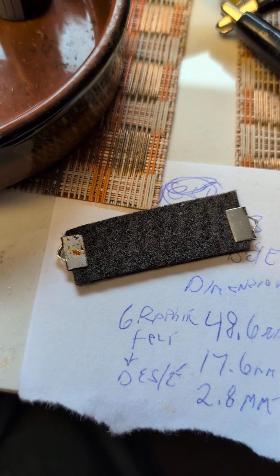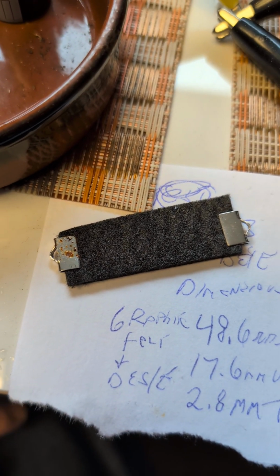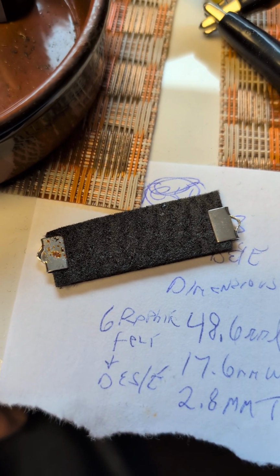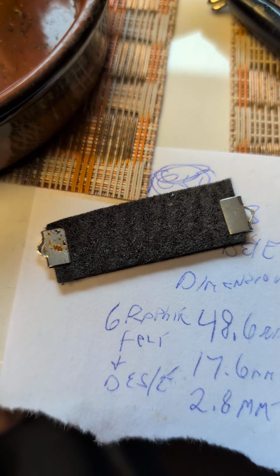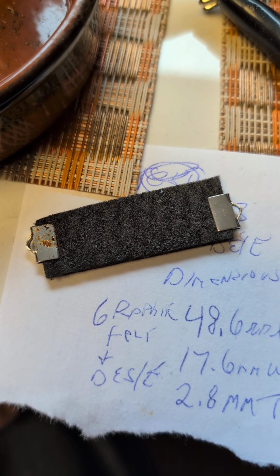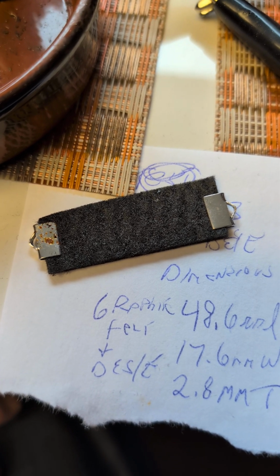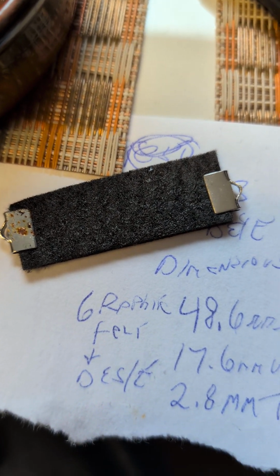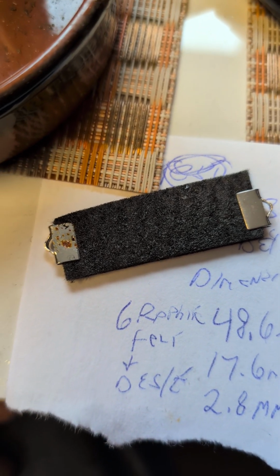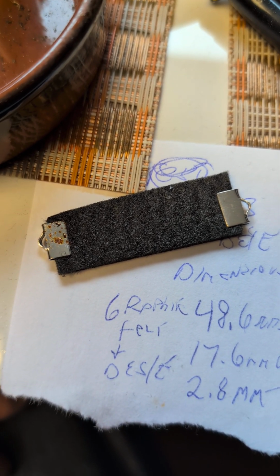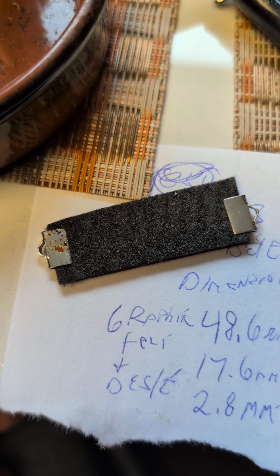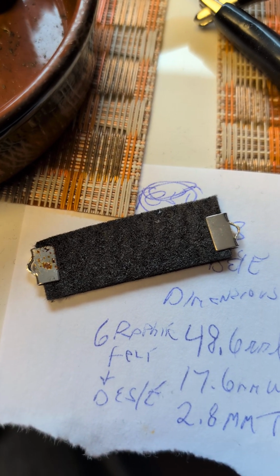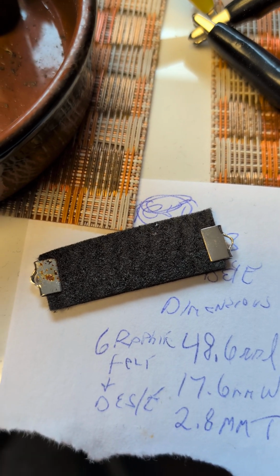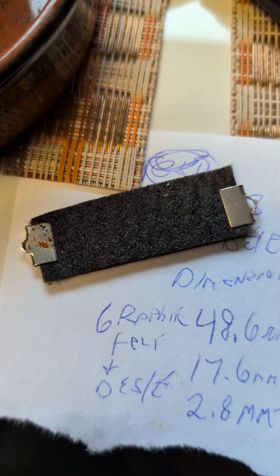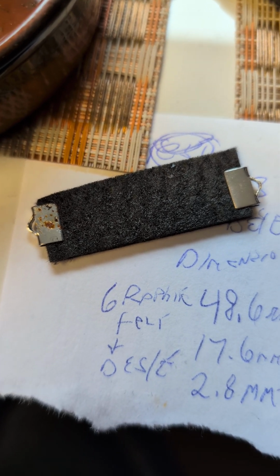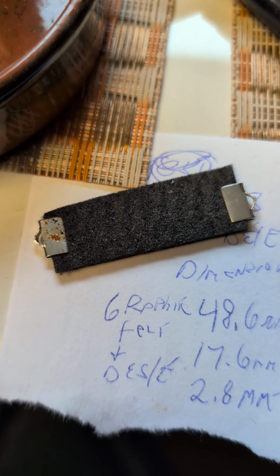I want to see if the DES electrolyte can hold up at 3.7 to 4.2 volts. And of course, we'll go up to about 500 cycles. In industry, they'll go up to 500,000 cycles. But if there's going to be a problem, we should be able to see it early on. And that's the value of this very simple first approximation before going on to using potentiostat, EIS studies. Actually, you're doing resistance measurements here due to the graphite component.